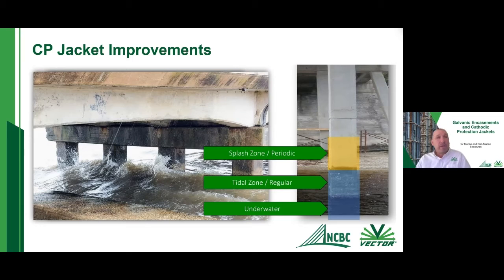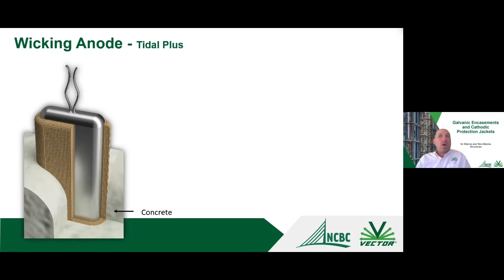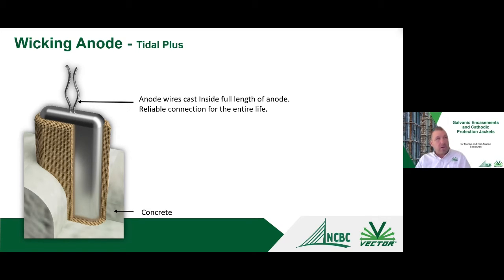So some of the improvements that have been made to the zinc mesh jackets are now going to allow it to not only protect everything in the tidal zone and the underwater zone, but to actually move up into that periodic zone, where storm events and so forth, or boat traffic, create a periodic splash zone. So what we're going to rely on here is, instead of a tidal jacket, a tidal plus jacket. And basically what we have is the concrete, and we have an anode that's going to be embedded in the concrete.